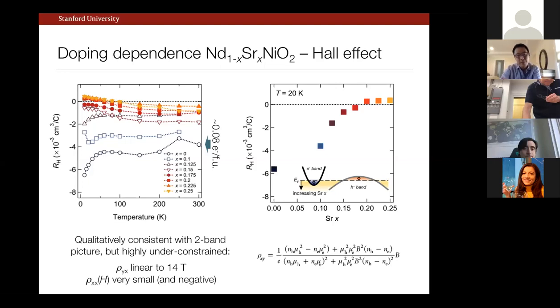So just to remind you, this is very different from, let's take graphene, for example. As I gate from electron doping to hole doping, the Hall coefficient itself is diverging on either side of that, right? And so in fact, the simplest picture one can have for this kind of continuous zero crossing is a multi-band scenario, namely a case where I have both electron and hole pockets in the system. I'll turn back to theoretical discussions in a moment, but if I have a system with, for example, this kind of configuration, even though we're doing hole doping, because we have this landscape of both hole-like Fermi pockets and electron-like Fermi pockets, at least that would be one self-consistent explanation of this data.